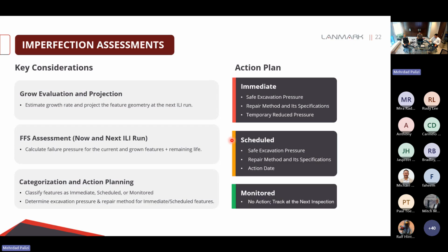For immediate and scheduled features, it is important to get the safe excavation pressure. This is going to be a percentage of the failure pressure and the amount of pressure at the time that the field crew are doing the repair over the pipeline. Also, we need the repair method and the specification for that. In the case of scheduled features, we should also provide the deadline for doing that repair.